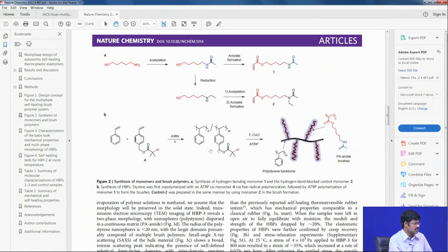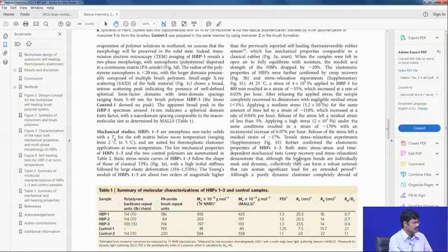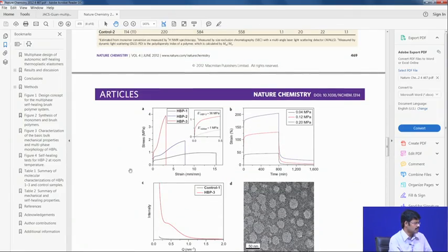So, if you change the ratio, you will change how much amount is there, and then if you control the ATRP, to what extent this grows, you can also control. So, accordingly you can prepare different kinds of materials which will respond differently to stress and strain.